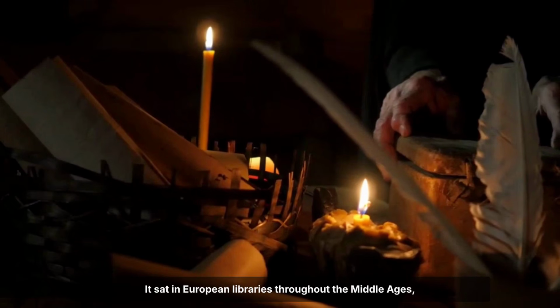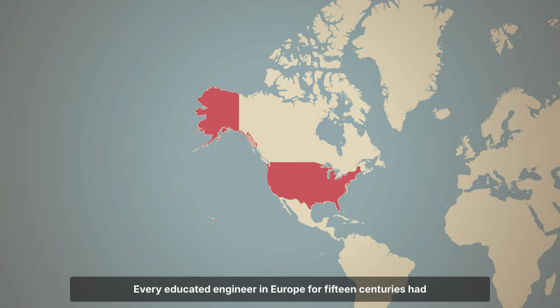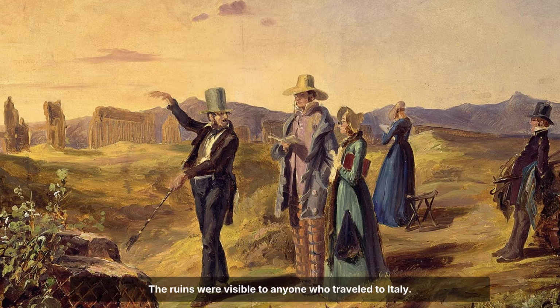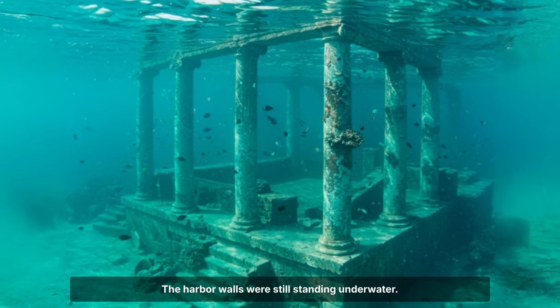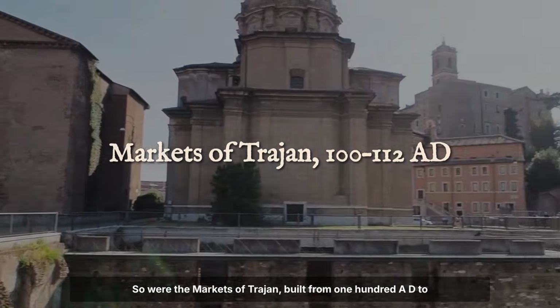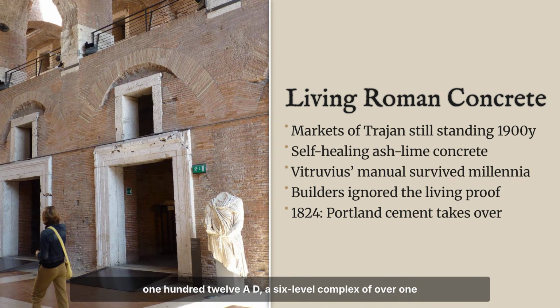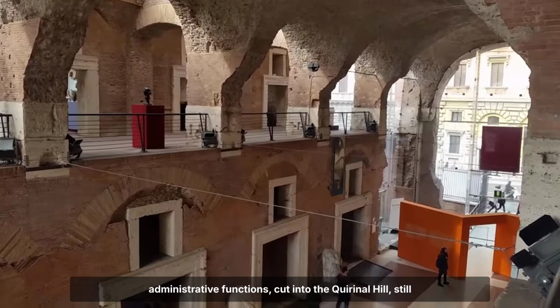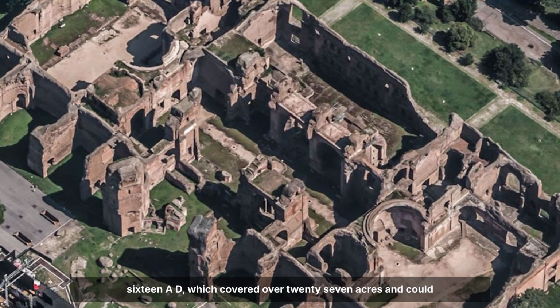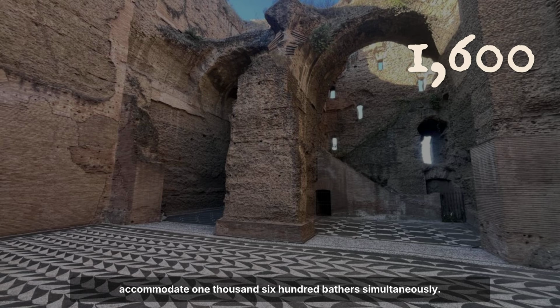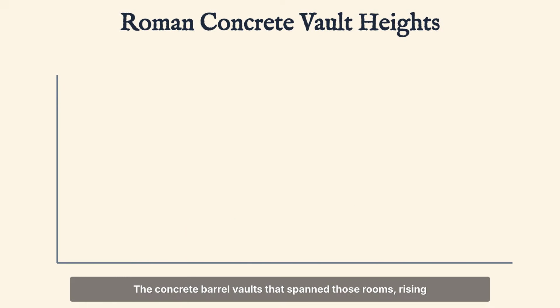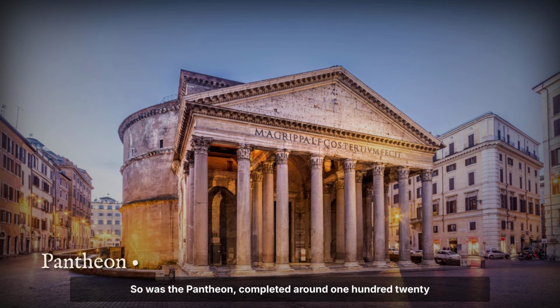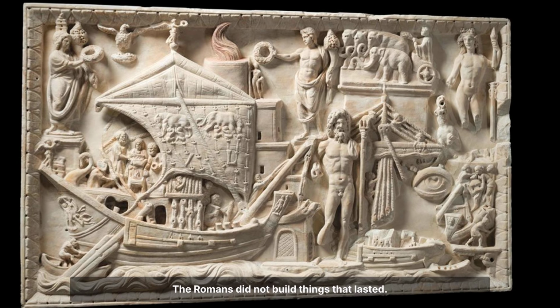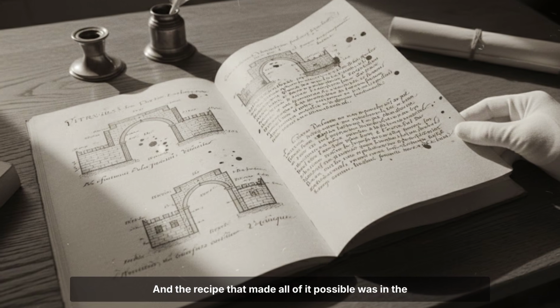It sat in European libraries throughout the Middle Ages, copied by monks, studied by Renaissance architects. Every educated engineer in Europe for 15 centuries had access to the recipe. The ruins were visible to anyone who travelled to Italy. The harbour walls were still standing underwater. So were the markets of Trajan, built from 100 AD to 112 AD, a 6-level complex of over 150 rooms housing shops, offices and administrative functions cut into the Quirinal Hill, still structurally sound nearly 2,000 years later. So were the baths of Caracalla, completed in 216 AD, which covered over 27 acres and could accommodate 1,600 bathers simultaneously. The concrete barrel vaults that spanned those rooms, rising over 100 feet without steel reinforcement, are still standing. So was the Pantheon, completed around 128 AD, its unreinforced dome still the largest in the world after 19 centuries. The Romans did not build things that lasted, they built things that improved, and the recipe that made all of it possible was in the library.